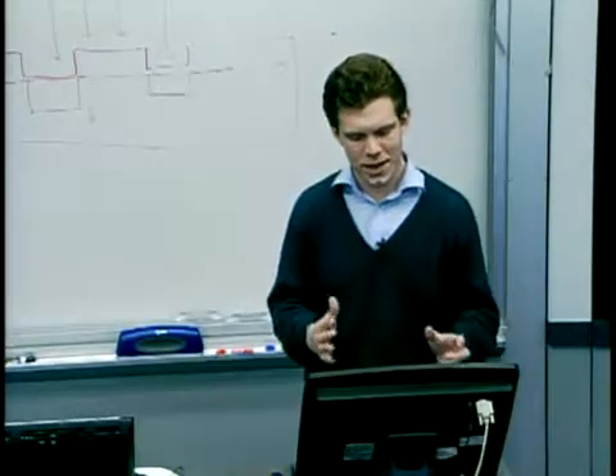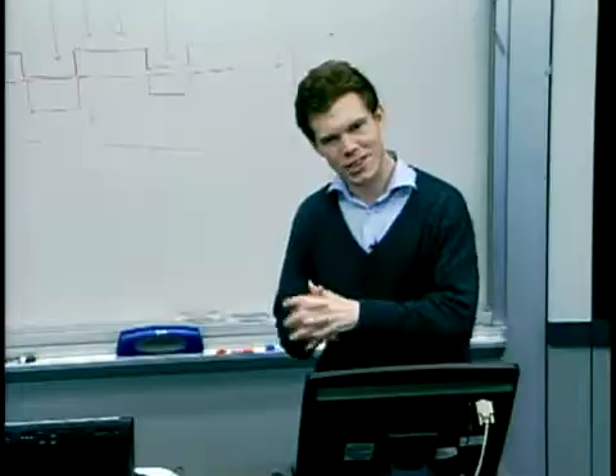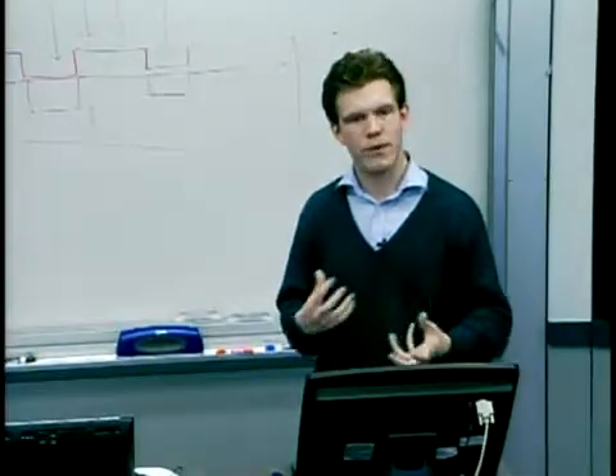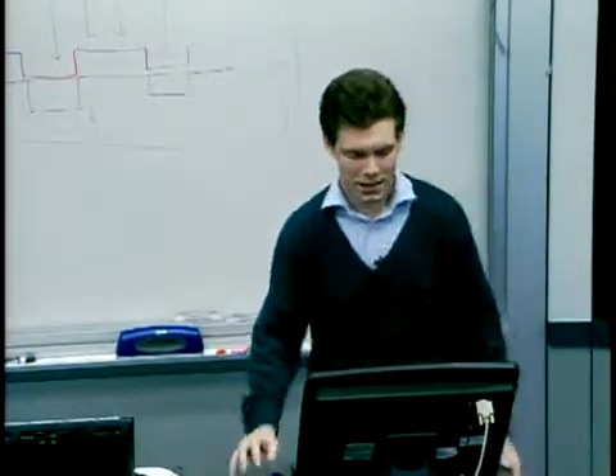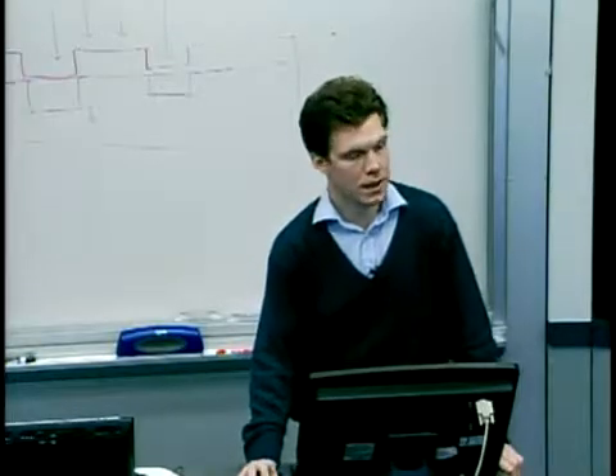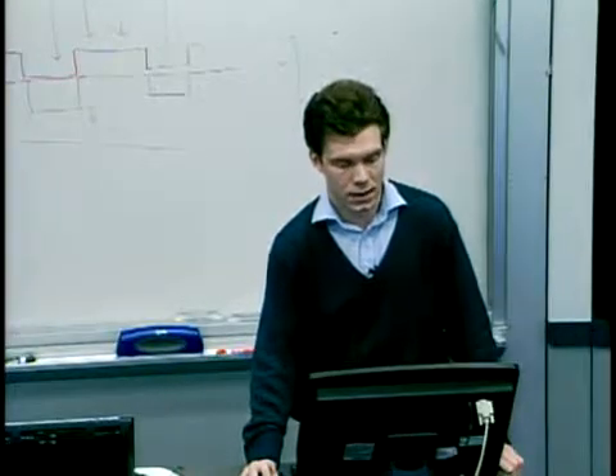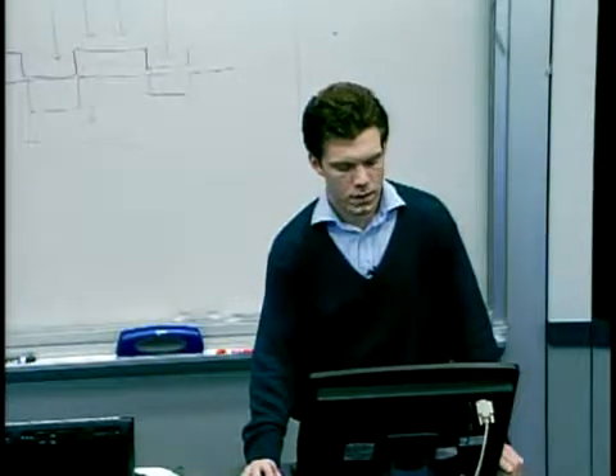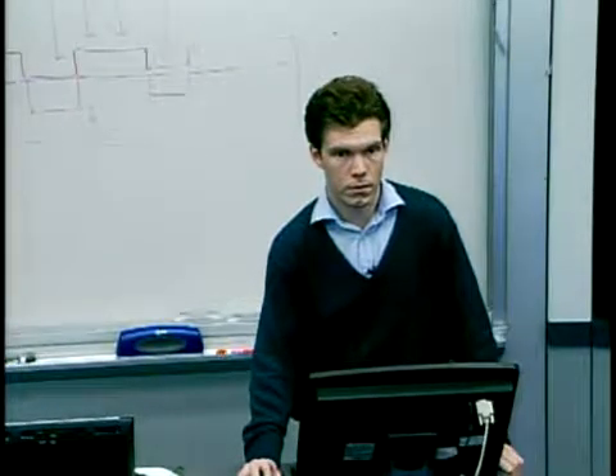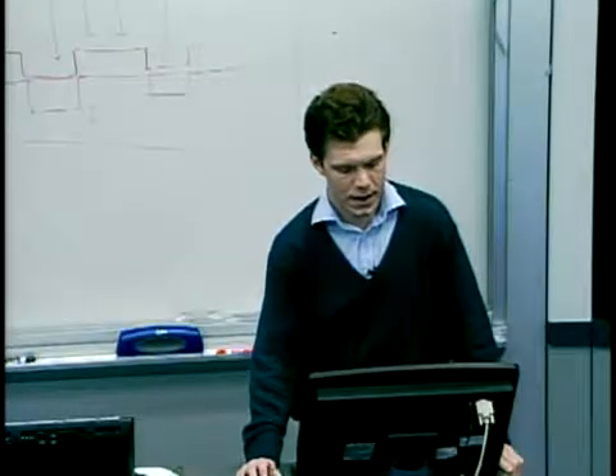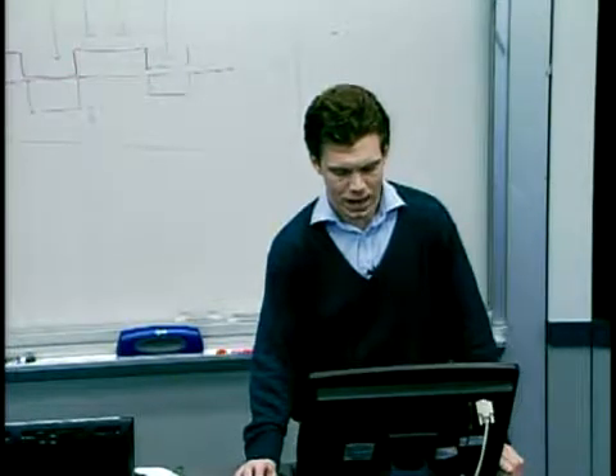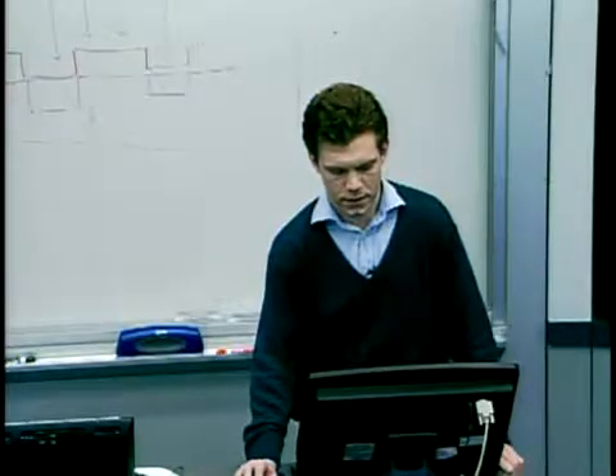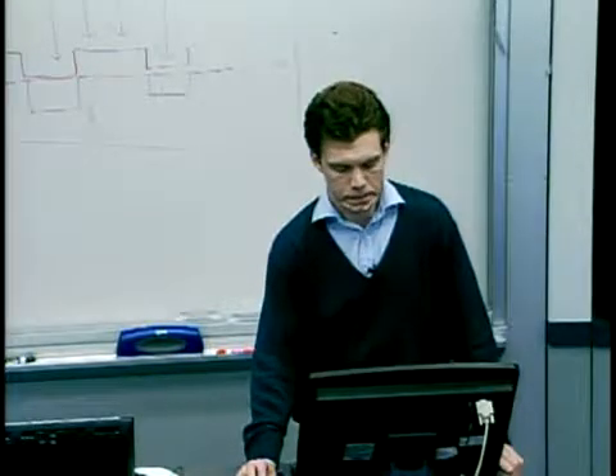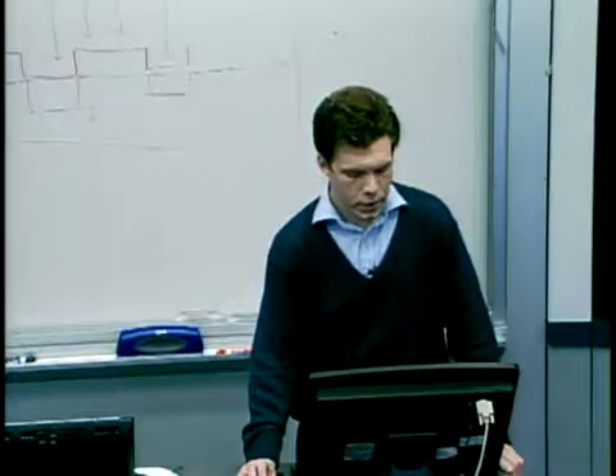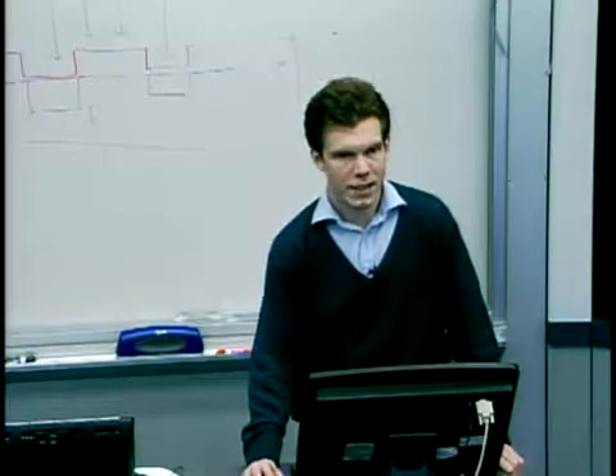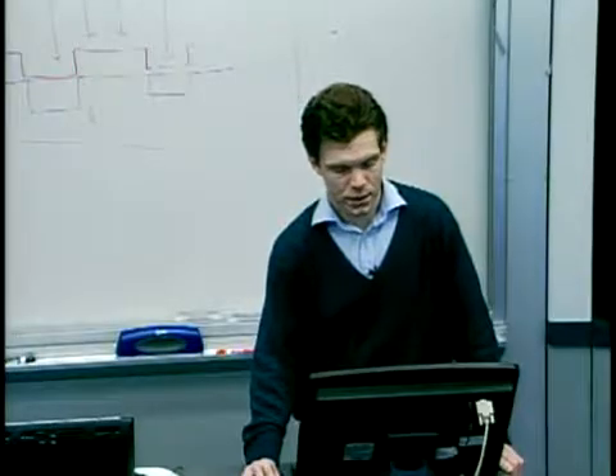So we're just using our zeroth order model to figure out what the Young's modulus of the material was, essentially. There's one parameter that we fit in doing the simulation, and that is the Young's modulus. Here are simulations done using that model. So we're roughly capturing the shape, and it seems to all stack up if we choose this Young's modulus, 5 megapascals at 130 degrees C. So that's all very well, but having these parallel channels doesn't give us too much information for a given experiment.